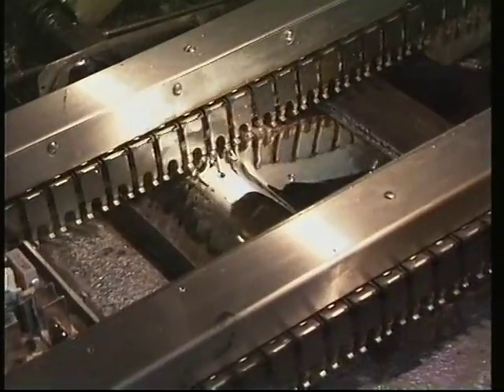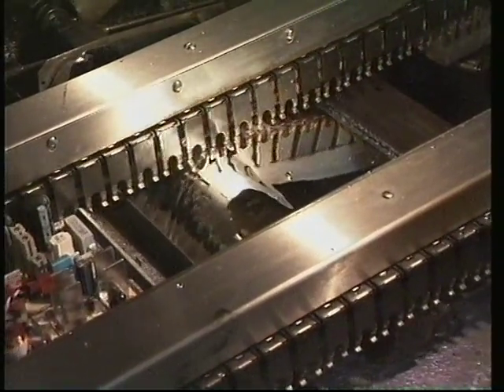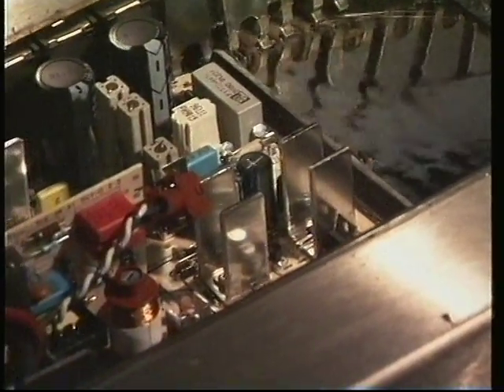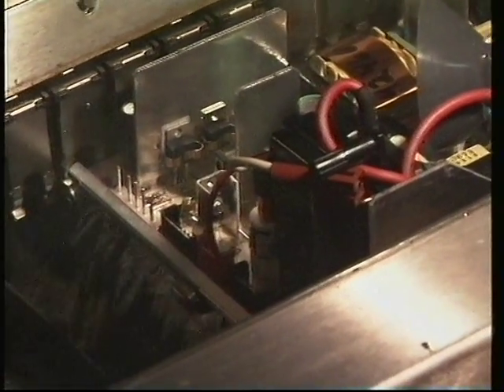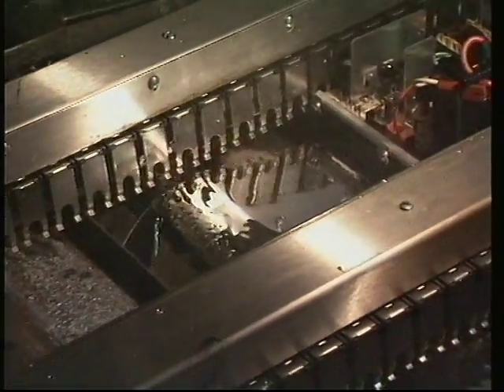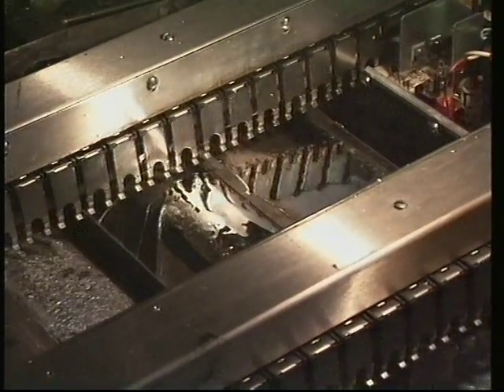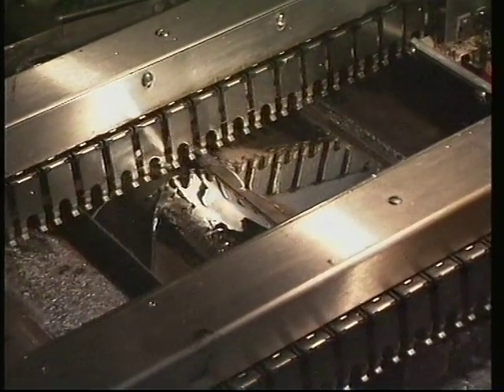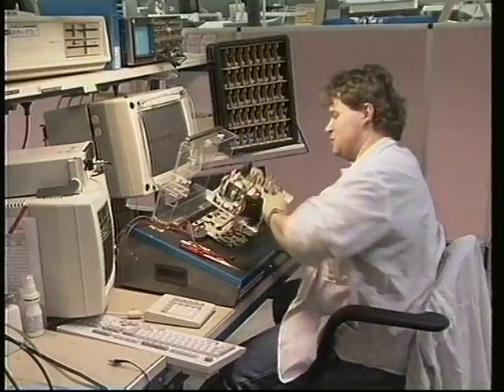Next, the board passes a wave of molten solder metal at a temperature of 240 to 260 degrees centigrade. The solder metal wets both the component leads sticking out of the board and the copper foil solder lands around the leads. When the board comes out of the wave, the solder remaining on the board solidifies and the joints are soldered.